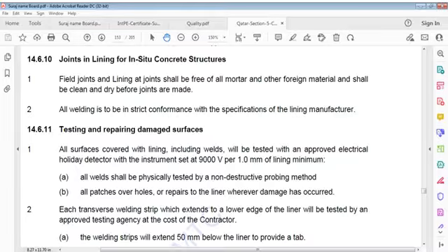So now we come to joints in lining for in situ concrete structures. Field joints and lining at joints shall be free of all mortar and other foreign material and shall be clean and dry before joints are made. All welding is to be in strict conformance with specifications of the lining manufacturer. Testing and repairing damaged surfaces. All surfaces covered with lining, including welds, shall be tested with an approved electrical holiday detector with instrument set at 9000 volts per 1 millimeter of lining minimum.